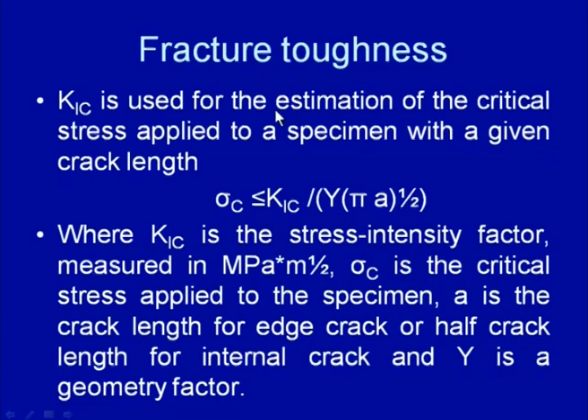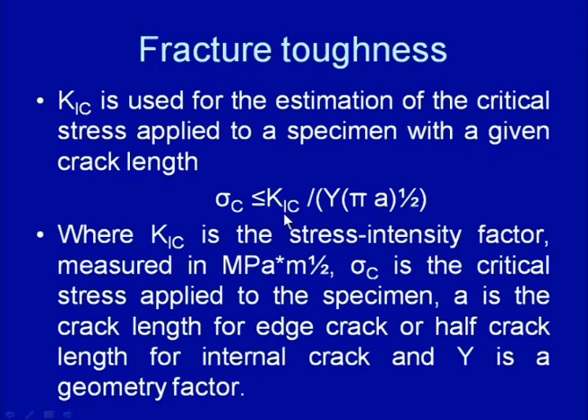Say, K1C is used for estimation of the critical stress applied to the specimen with the given crack length. So, if the critical stress intensity factor has been identified and we know the crack length, then we can identify the critical stress required for catastrophic failure of the component. K1C is the material parameter, and with the crack length known, we can assess the critical stress which will be required for propagation of the crack.